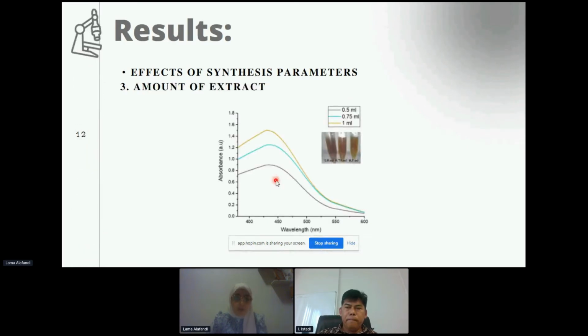The third parameter is amount of extract. Here we increase the amount of extract from 0.5 milli to 1 milli, also with 60 Celsius incubation temperature and 45 minutes. Here we can also see the solution is getting darker, meaning more silver nanoparticles are formed as well. And here we see the peak of formation is at the same wavelength as well, so we assume it's the same size and shape. And here the justification that more amount of extract causes more formation of silver nanoparticles, because when the extract is increased, that means there are more bioactive compounds in the solution which can interact with silver nitrate and reduce it.